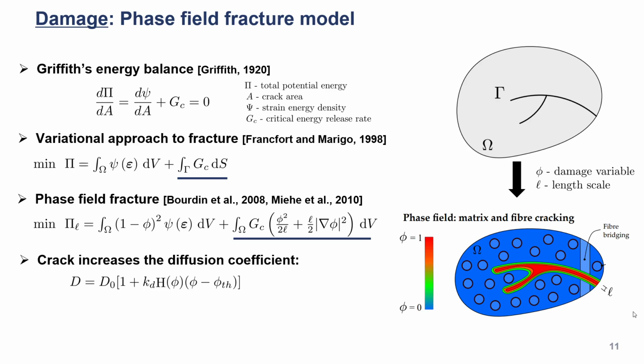The last thing we want to consider here is that the crack can actually increase the diffusion coefficient. In that sense, when the crack happens, the open area can serve as the weak spot to promote the moisture diffusion.